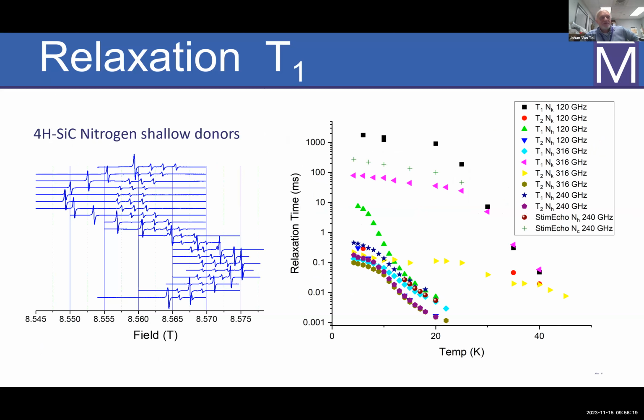So for the T1 relaxation, things are a little bit different. And this is an example in silicon carbide. So these are nitrogen shallow donors. It's somewhat comparable to phosphorus in silicon, except that this is a hexagonal crystal and there is quite a bit of anisotropy. And you have two different sites in this particular polymorph of silicon carbide. There's a cubic center and a hexagonal center. So the cubic center has a much larger hyperfine splitting with the nitrogen. It's also there, of course, in the hexagonal center, but it's less well resolved.